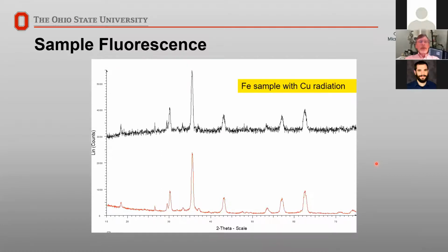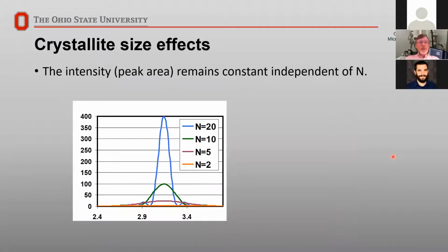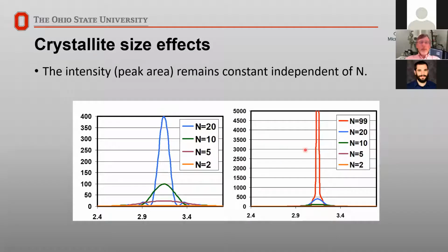So as we're looking at crystal structures, one of the things that we find is that as we make our lattice or our crystal very, very small, our peaks get wider. So if we start looking at the number of unit cells, those cubes in the crystal, if we're down to 5 unit cells, we get a very, very wide peak, not very well defined. As we increase the number of unit cells, our crystallite size gets bigger. You see that our peak gets a little bit sharper and gets a little bit sharper as we get up to 20. And by the time we're up to about 100 unit cells, our peaks are getting pretty sharp.